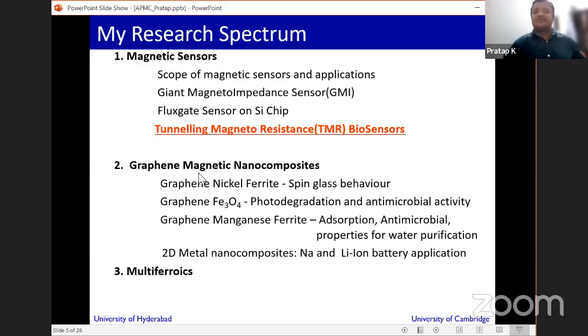My other research is 2D material metal nanocomposites, where metal nanocomposites plus 2D material are mixed together as a nanocomposite. We have observed spin glass behavior in graphene nickel ferrite, and we formed a graphene ferrite. We studied it for water purification applications, antimicrobial activity, and all this. We prepared graphene manganese ferrite, and we used it for adsorption, antimicrobial, checking water purification and all this. And currently I am engaged in sodium ion and lithium ion battery materials, focusing on electrodes and especially anodes. We also work on multiferroics, so bismuth ferrite, doped bismuth ferrites, composites, both in nano powder and thin film form.